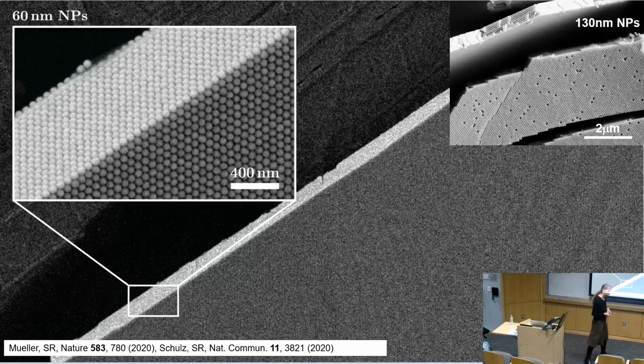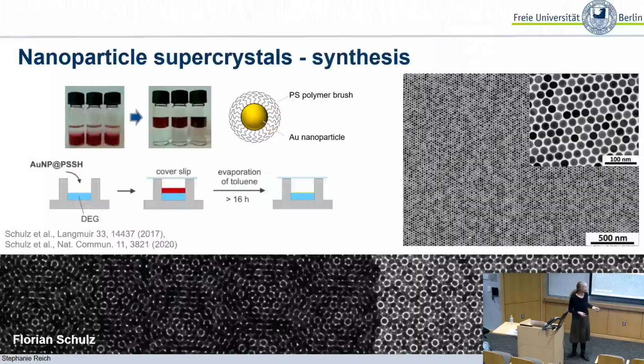Yeah, I had a question. I have two questions. So previous slide, some particles are darker than the others. Why? That is essentially different concentrations that he used. No, here. These are the different facets of gold you're looking at, so they are oriented slightly differently. And whether you look down the 111 direction or 112, that makes a difference in the contrast. So this misorientation of the facets plays no role whatsoever in the... No, they're too big. The wavelength is too big. Well, the gold nanoparticle is too big.